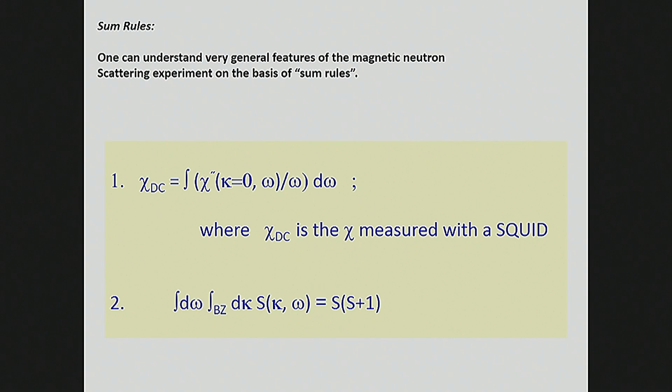So if your magnetic moment for manganese corresponded to spin 5/2, then for a particular manganese-based compound, the integral over all that inelastic scattering would basically go like S squared. It'd be 5/2 × 7/2, okay? Compare that to the case where everything was exactly the same, except you change the manganese 2+ to copper 2+. Then the integral of all that scattering goes from 5/2 squared, basically, to 1/2 squared. Right. So it goes way, way down because it goes like S squared. It's not really S squared, it's really S times S plus 1. But the intensity that you measure over an entire Brillouin zone and all energies is given by a sum rule, and the sum rule just depends on the moment size. And with that, I think I'm sure I'll finish, in fact. Yeah, okay. So thanks.